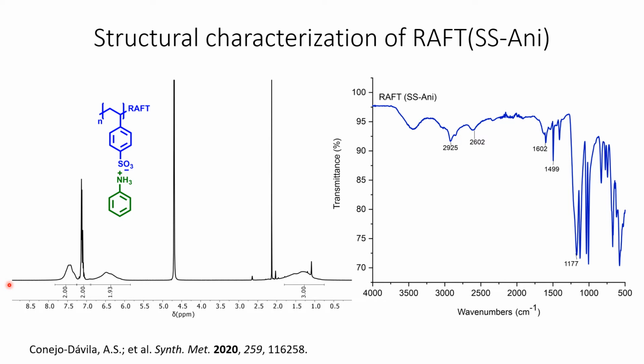Structural characterization of the ternary system and its intermediate products. To elucidate the structure of the macro-RAFT agent, we use NMR spectroscopy and FTIR spectroscopy. The proton NMR spectrum shows the aromatic protons of the benzene sulfonate substituent, also the aliphatic protons of the polymer backbone, and the aromatic protons of the anilinium ion. If we compare the integration of the anilinium ion and the benzene sulfonate, we can deduce that only 50% of the polymer was functionalized.